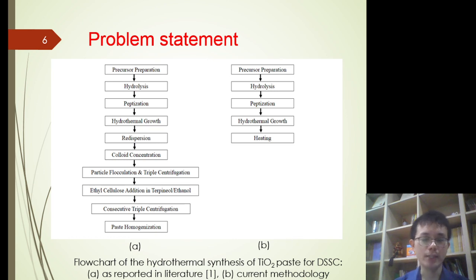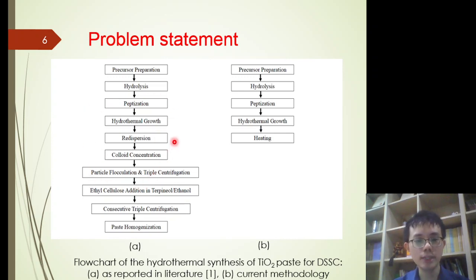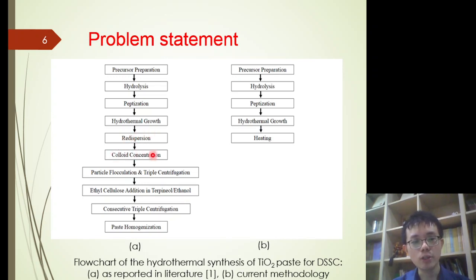Here is a conventional flowchart of the hydrothermal synthesis of the titanium dioxide paste for the DSSC. The left-hand side shows the methodology as reported in the literature, while the right-hand side shows the methodology adopted in the current research. The literature methodology involves several additional steps such as redispersion, colloid concentration, centrifugation, and paste homogenization, which requires the use of specific instruments such as the sonicator, rotary evaporator, centrifuge, and three-roll mill, all of which complicate the whole DSSC processing.